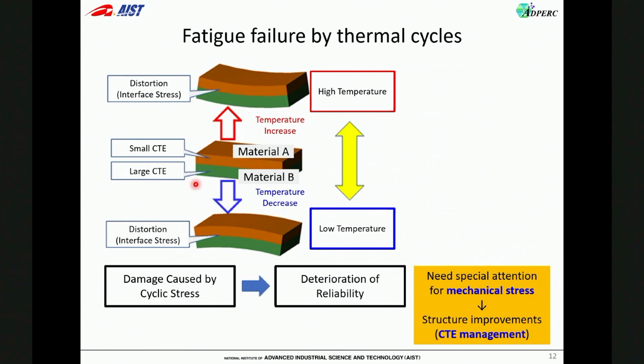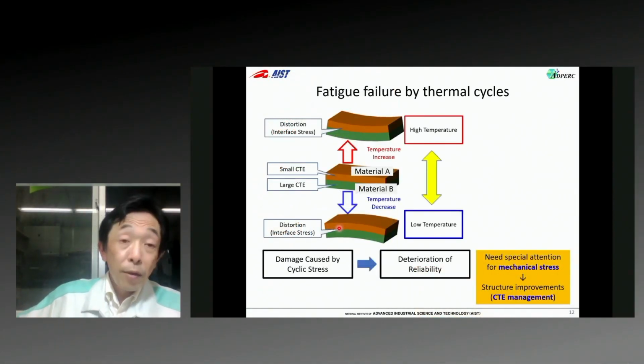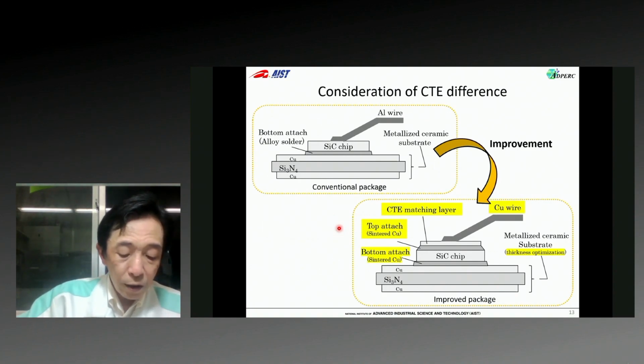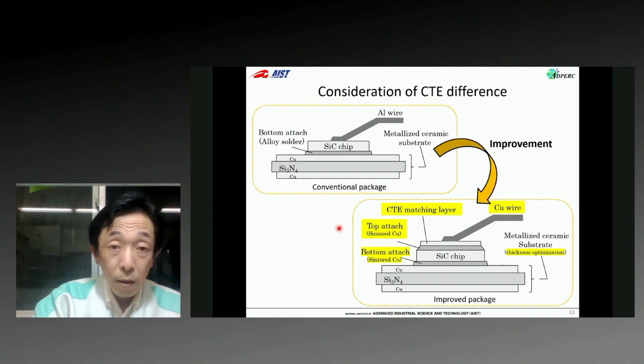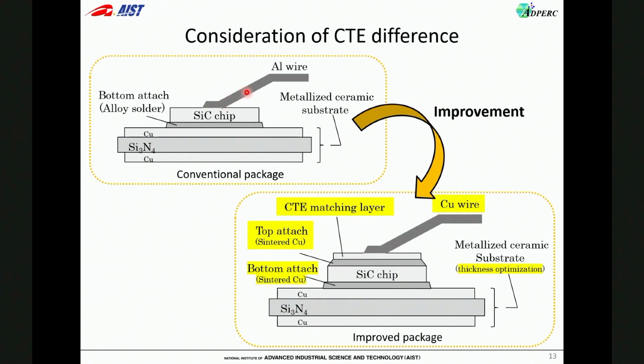As shown here, the mechanical stress is applied to the contact interface when the temperature changes. The stress leads to fatigue breakdown in the interface since the stress is applied repeatedly here and here. Thus, the mechanical design has to be changed in order to improve the endurance for the stress. The wire material is changed from aluminum to copper because of the mechanical strength under high temperature. In addition, a CTE matching layer and top attach are changed in order to reduce the CTE difference between copper and silicon carbide.